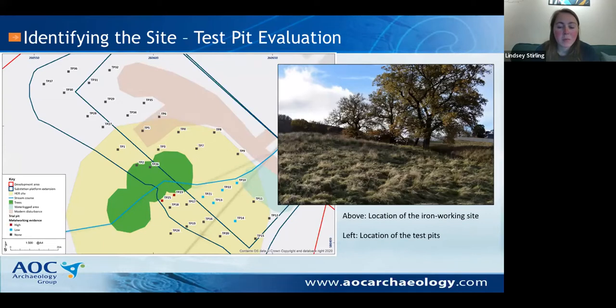But when we started digging pits on the south side of the stream, several of these pits contained quantities of slag, especially the ones on the slope. We could see pieces of slag in the stream bed as well. And in particular, two of the test pits, 23 and 25, contained really high concentrations of iron slag. And these were pretty much at the top of the slope, right underneath this stand of oak trees that was in the center of the site.